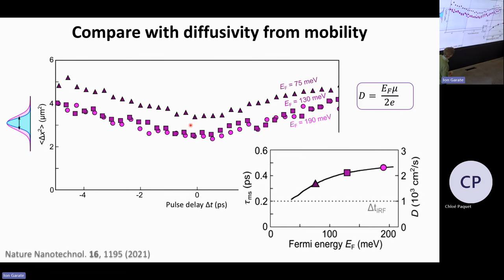So what we did is that we measured the mobility. Through four-probe measurements, what I show here is the momentum relaxation time, which is of course related to the mobility. And it's on the order of a few hundred femtoseconds. So we have quite high mobility samples. It's a few hundred femtoseconds before you get momentum relaxation. And you can connect that to, we of course also know the Fermi energy. So with slightly higher Fermi energy, you get a slightly longer momentum relaxation time. And then through this equation, we can get the diffusivity, which is on the order of 2000 centimeters squared per second. Okay. So let's plot a diffusivity of 2000 centimeters squared per second into our data. And it actually fits quite nicely. So we were very reassured when we saw this. Also slightly disappointed because, of course, it means that everything makes sense. So there's nothing exciting about it.